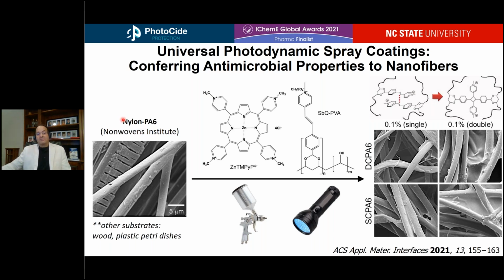And so we took those nylon nanofibers, but we can do this with wood or plastic or any other substrate, and we spray coated them with our bicomponent mixture, subjected them to a UV cure. And again, whether it was dip coated in the top or spray coated at the bottom, you can see that we've created this very nice web of our photocross-linkable polymer, into which has been embedded the photodynamic agent, which is the drug that is going to be inactivating the pathogens.